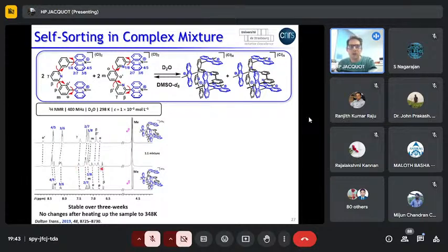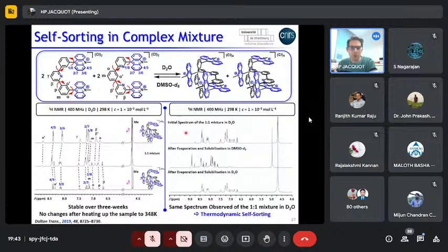It's as if we have reached thermodynamic equilibrium. To make sure of this, we took this same sample, evaporated the D2O, and put everything into DMSO. What we expect is to dissociate the dimers into the corresponding monomers. Why do we want to do this? It's like when you play poker: you want to shuffle the cards in order to have a new game. That's exactly the same idea behind this. Then we evaporated the DMSO again and added D2O, and you see that you have exactly the same spectrum as before. So this means that indeed we are under thermodynamic control.